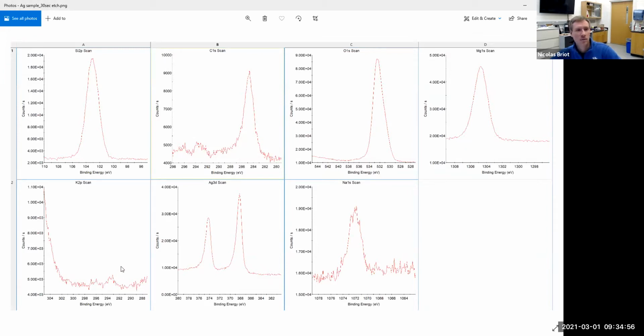So the question we had in EDS was, do we see potassium in that sample, because the potassium peak is very close to the silver one. Well, the XPS tells me that you have no potassium. Even at the top surface, you get no potassium in that sample, just silver.